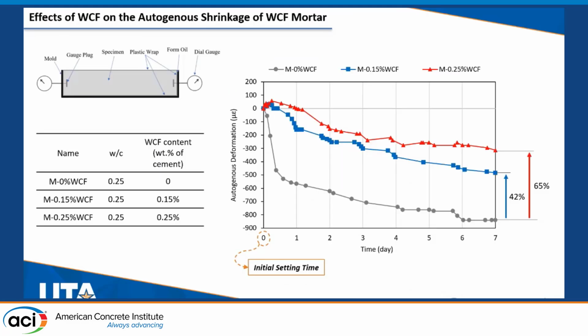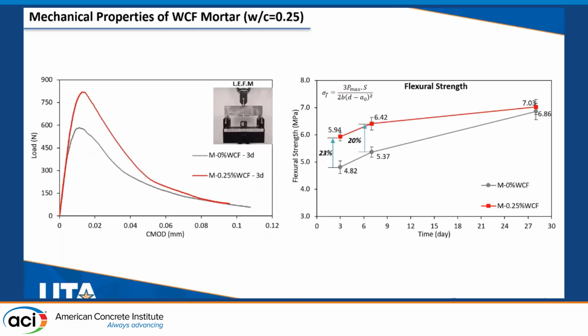Starting with autogenous shrinkage, I measured the autogenous deformation of WCF mortars at a very low water to cement ratio at different dosages, which led to significant reductions of autogenous deformation of up to 65% for our 0.25 weight percent of cement sample after 7 days of hydration. Then next is the mechanical properties.